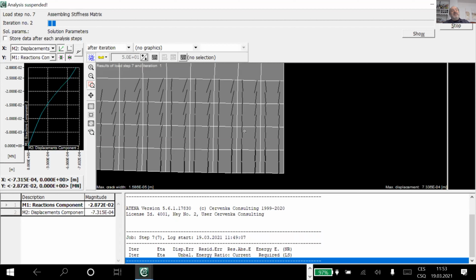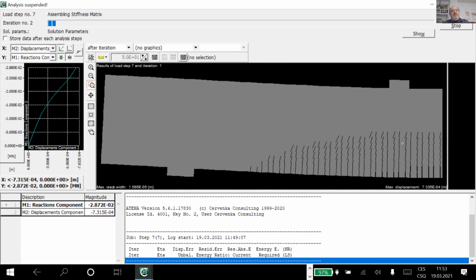These cracks are reproduced in integration points. On each finite element, we have 4 integration points, and here there are 4 lines on every finite element to show the actual situation in the particular finite element. For example, here you can see there are 3 cracks in 3 integration points, material points, but the last one is still undamaged. Well, okay. In the post-processing, usually we show the crack just per finite element, which is often nicer just for the graphical representation.